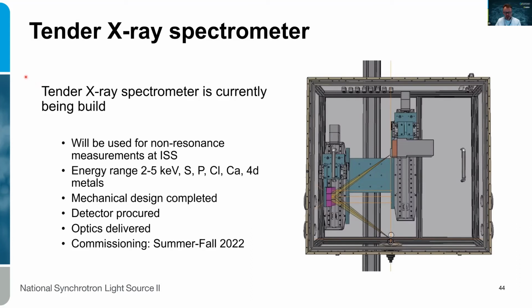One interesting development that again is led by Dennis is the tender X-ray spectrometer, which is being designed now in different parts. This is going to serve our users that, together with the elements above titanium, are interested in the chemistry of sulfur, phosphorus, and low lying edges of 4d and 5d elements. This setup will cover 2 to 5 kiloelectronvolts. We cannot go there to do resonance measurement, but even the non-resonance emission spectroscopy will be a huge help for those trying to learn something about those lighter elements or edges that are more sensitive to changes in electronic structure. We hope to commission this instrument sometime in the summer or fall of this year.